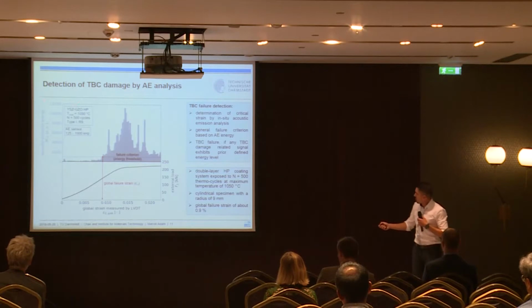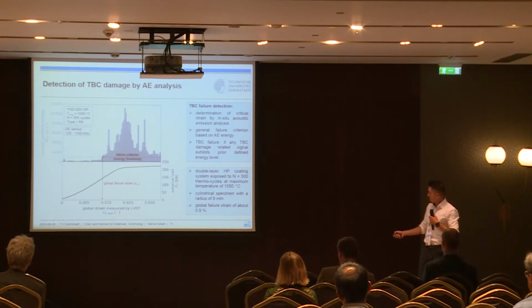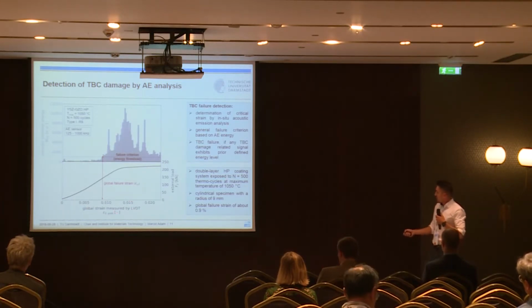And we have on the vertical axis the acoustic emission energy, on the horizontal axis the globally measured strain, and here's another secondary vertical axis, which is the external load we applied onto our cylindrical specimens. And as you can see here, if we apply a load, there is a long range where nothing happens. This can be clearly seen in the low level of the acoustic emission energy signals we got from the TBC.